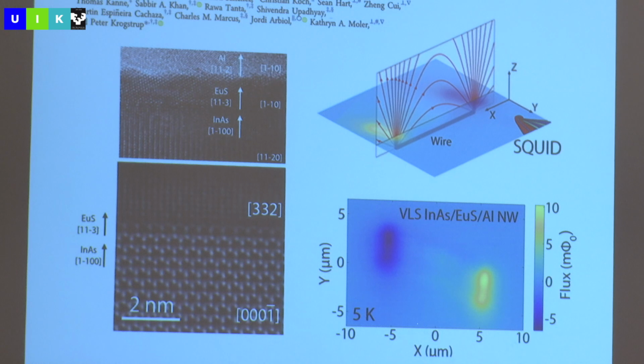It's not planar. It's crystalline, but it's not planar, and there's rough spots, and the rough spots are serious. But the growth directions are in a 2-to-1 ratio at the interface between the indium arsenide and the europium sulfide. So what we did was a collaboration with Kathryn Moler at Stanford University, used this to measure the magnetization of these wires, and saw the important observation was that you only get magnetic fields at the ends of the wires.